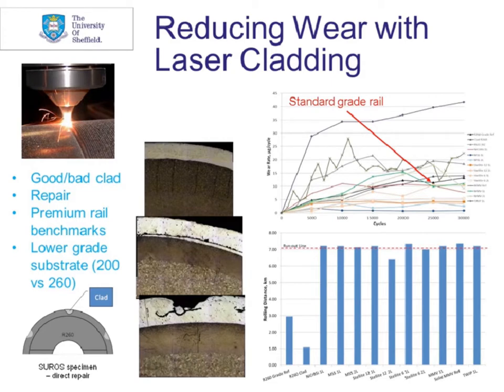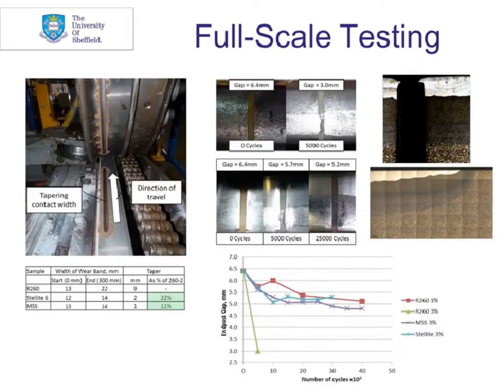Of course, this has been done on twin disc testing, so a very simplified contact. We needed to look at how it fared in a full-scale scenario to build confidence and to get permission ultimately to get it out into track. So we clad some rail and we ran some wear tests. We were getting very much lower wear rates with the cladding, which reflected the scaled twin disc testing results.